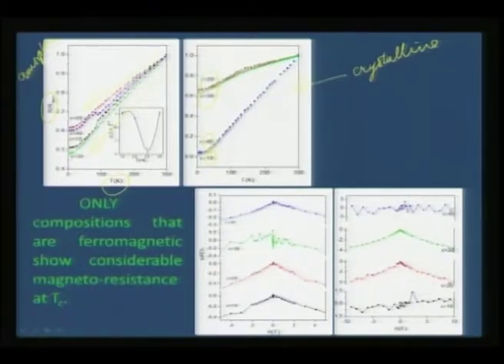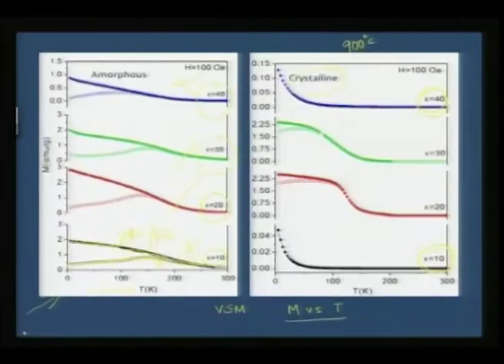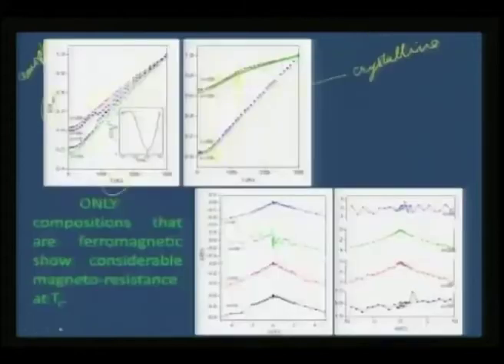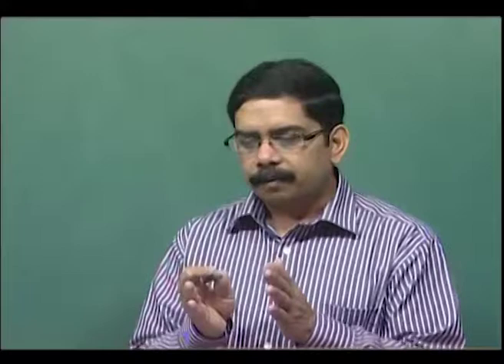And as you would see here in this rho versus T plot, it is linearly decreasing, whereas in the case of the true magnetic phases, you can see there is a small change in the slope, especially in the place where there is a TC. As you would see here, I just want to point out, because the TC is somewhere here, as a result you would see a small inflection here going hand in hand. So, the magnetic phases show a different rho versus T behavior compared to the amorphous pattern.